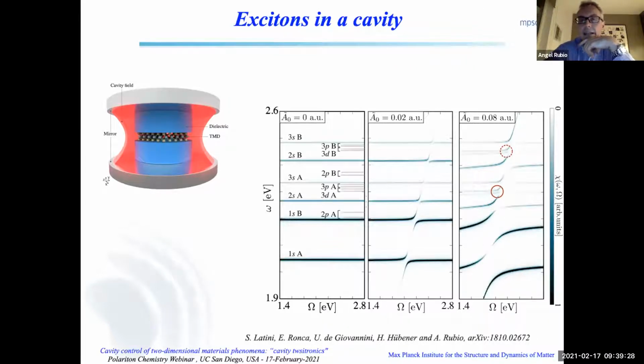What are those states? What I didn't show before is that those are the bright excitons, but then you have the dark excitons of the molybdenum disulfide. And if you see, those dark excitons become slightly activated by the coupling to the cavity. This is a quite interesting mechanism, which is also borrowed from atomic physics, in doubly excited states, in which they get oscillator strength in linear response by being close to a single excitation. Here it is the same: you are getting oscillator strength because those dark states become close to a bright state, which is the one that is being split into the upper and lower polaritons due to the coupling of the exciton to the cavity mode.